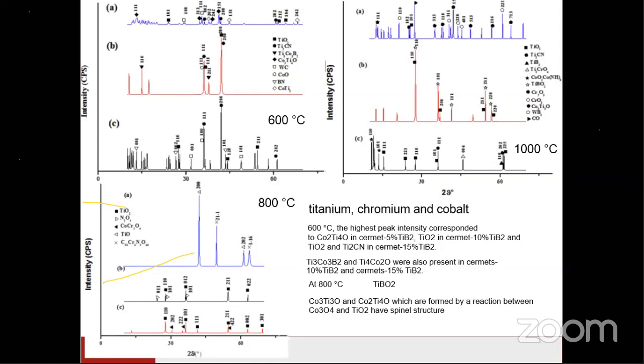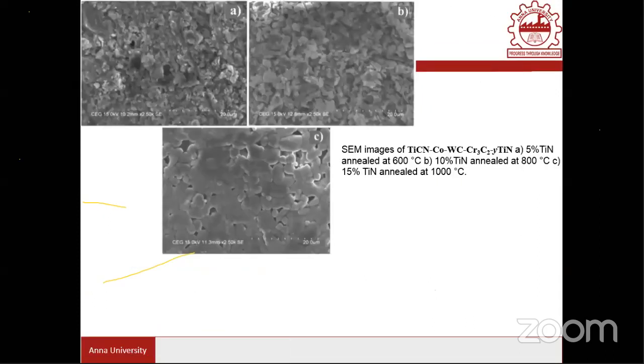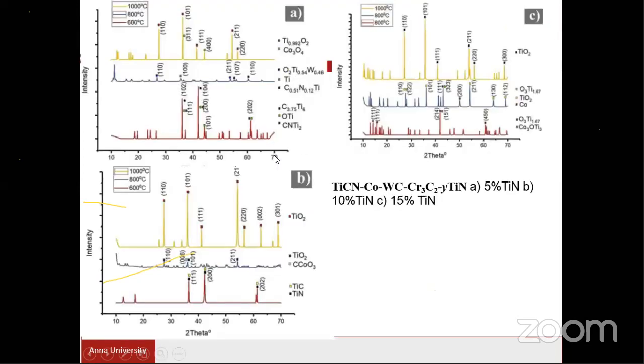Look at TiO2, TiC, Cr3C2, Cr2O3: chromium is transforming into chromium oxide. So more compound oxide phases were formed after 800 degrees centigrade. Up to 800 degrees centigrade, the formation of oxide was also there, but it is very limited. But at 1000 degrees centigrade, all these elements were converted into oxides. Likewise, the titanium nitride variation in the composition was also subjected to the annealing cycle, which shows grain growth at 1000 degrees centigrade, and also a lot of oxide formation at 1000 degrees centigrade.